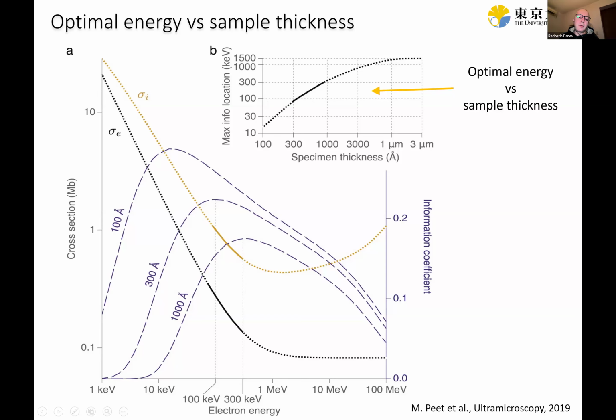So 300 keV at the moment is the highest voltage we have in practice for cryo-EM experiments. Hopefully in the future there will be some prototypes exploring higher voltages, for tomography especially, but at the moment this is what we have. But in any case, 200 keV at 50 nanometers and 100 keV at 30 nanometers, this is something we have to consider.